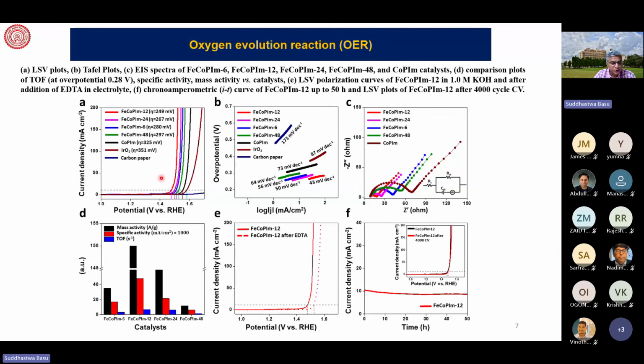For the oxygen evolution reaction, the best catalyst, or the benchmark catalyst, is iridium oxide. That has been put in all the PEM electrolyzers. We use iridium oxide. Ruthenium oxide is the best, but it is not stable, and so we use iridium oxide. Some people use iridium ruthenium oxide, but mostly the benchmark catalyst is iridium oxide.